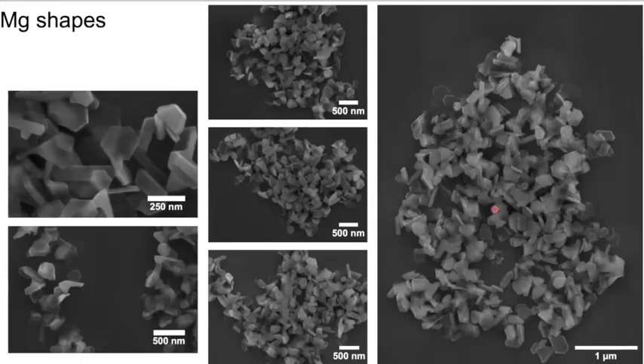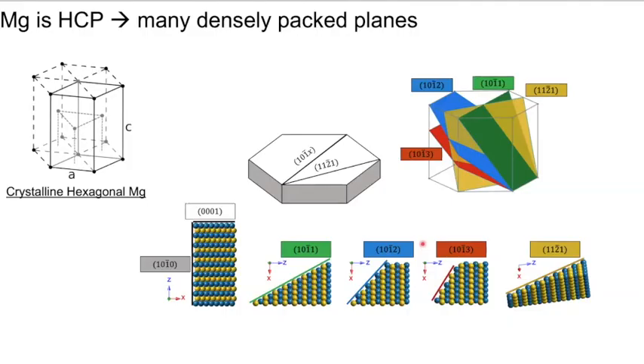And these particles are nice and sharp and faceted, like you would expect for gold or silver that's been colloidally produced. But they are not like gold and silver because they do not have the same crystal structure. Magnesium is hexagonal close-packed. Gold, silver, copper, aluminum are all face-centered cubic. That means that they have different crystallographic facets that are low energy. And that in turn means that they have different thermodynamically stable shapes.